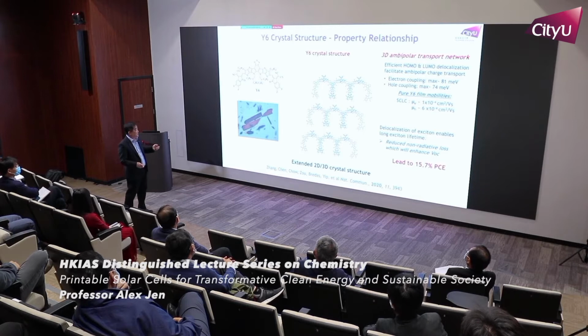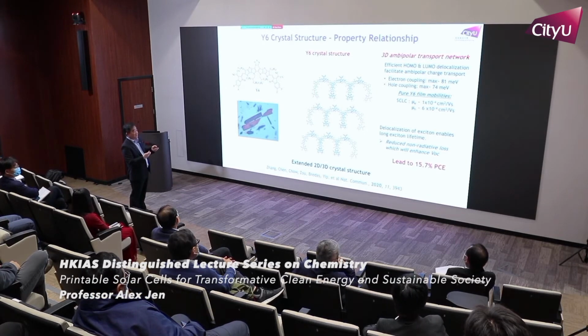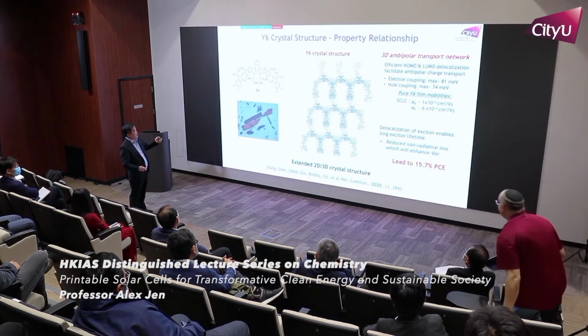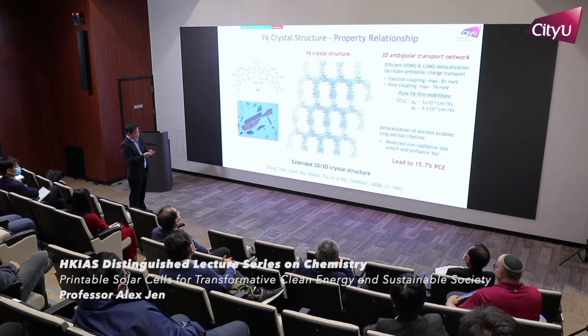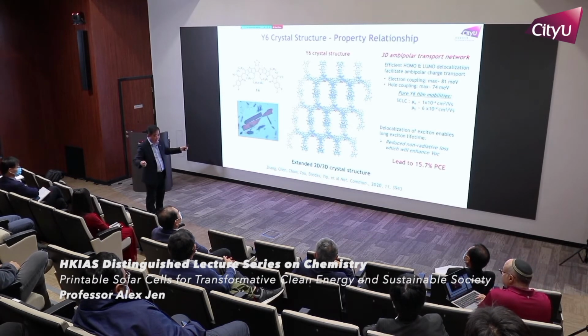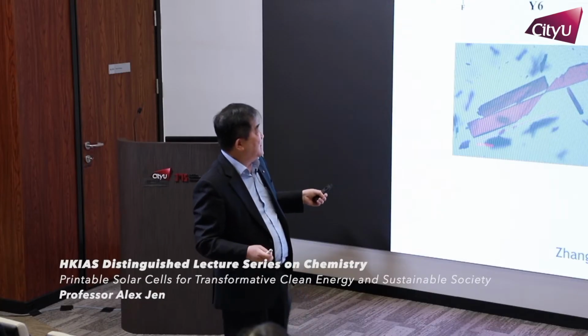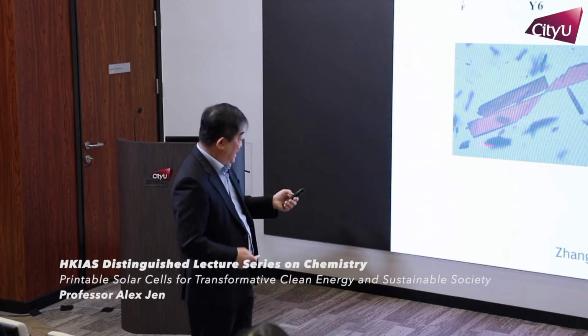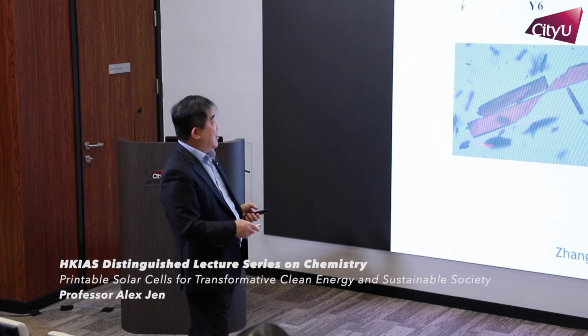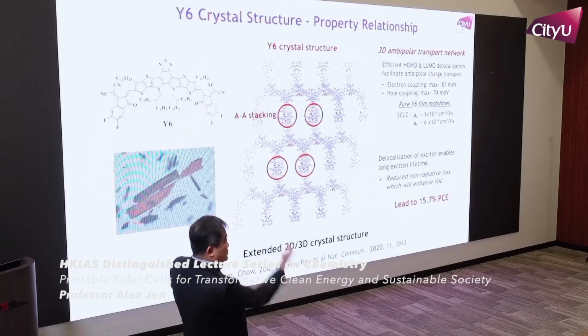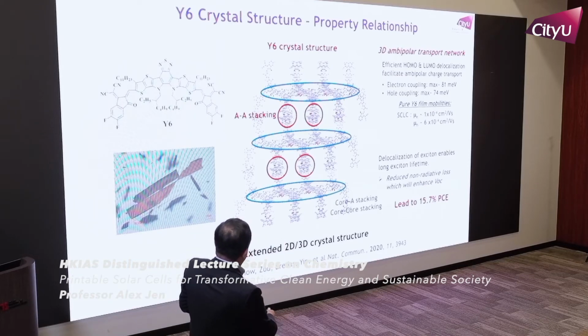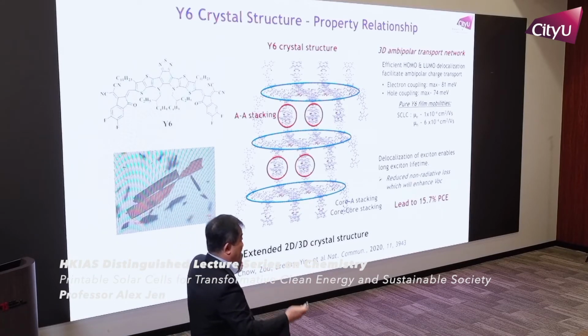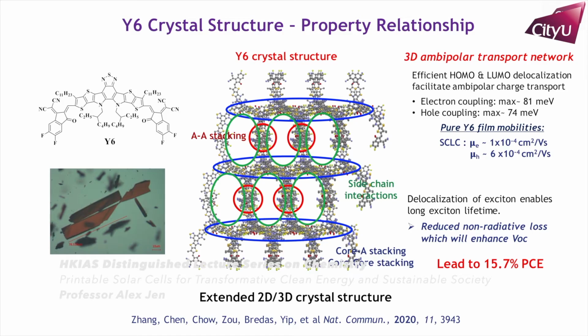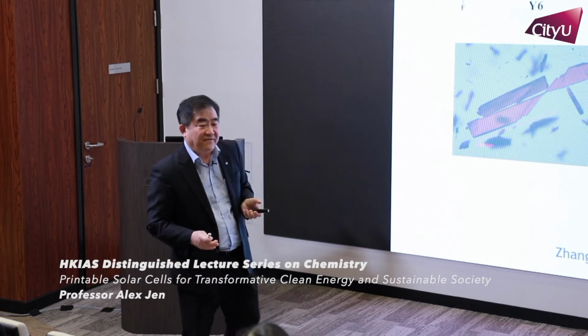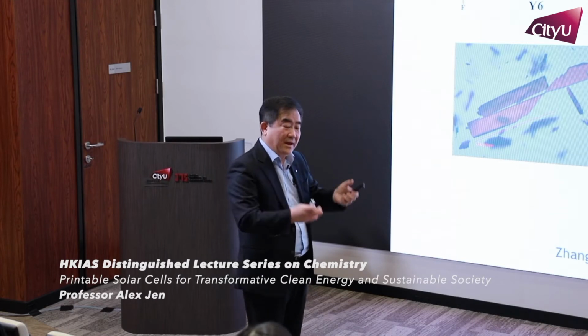And then when this molecule starts to crystallize, they start to pack through molecular interactions, and then you can see the packing. From the acceptor, you pack in a linear chain, like one-dimensional, then start to form two-dimensional, and then stacking on top of that, it becomes three-dimensional. And this becomes very interesting because all the stacking of those acceptors forms a very nice electron transporting channel, okay? And the overlap of all the cores becomes the backbone for transporting holes. Then the side chains stick into this core, so they perfectly, without causing steric hindrance, don't twist your backbone too much. So this is actually a very intelligent molecular design resulting in a very nice crystal.